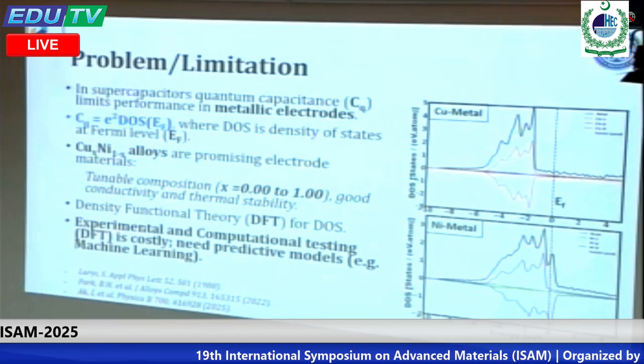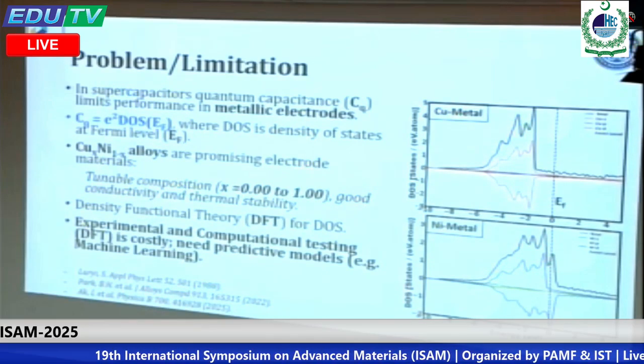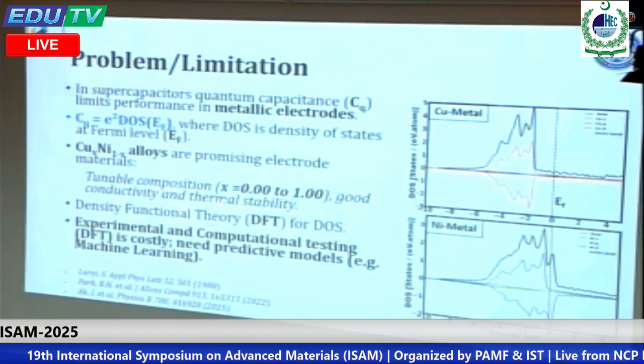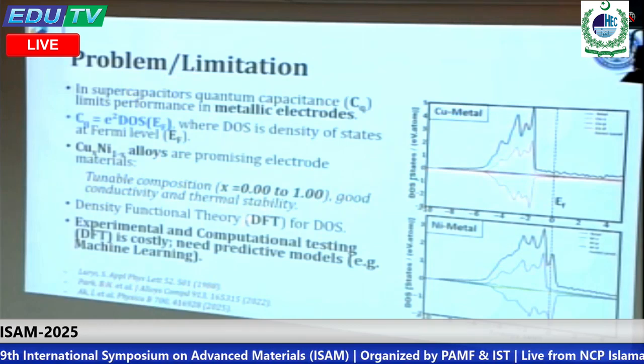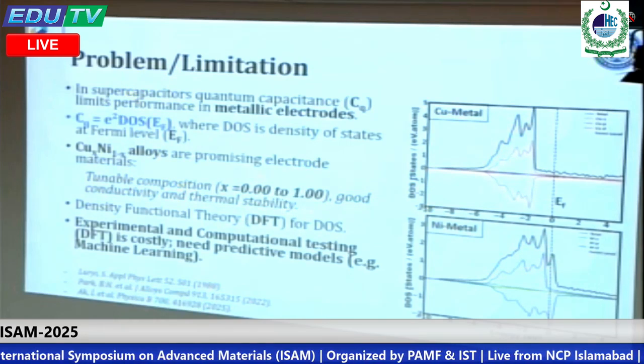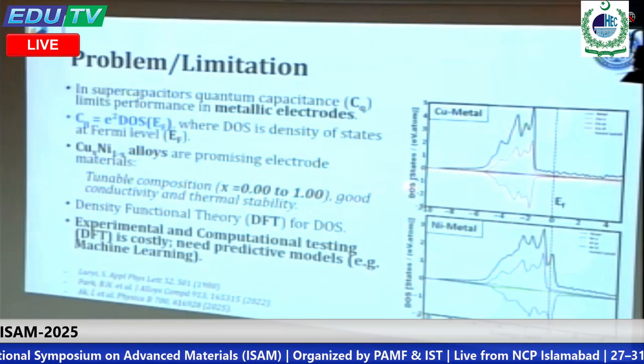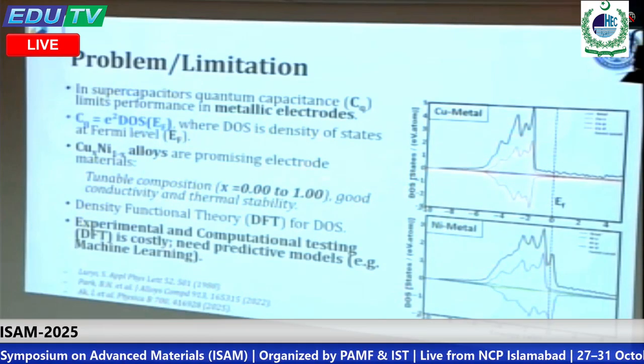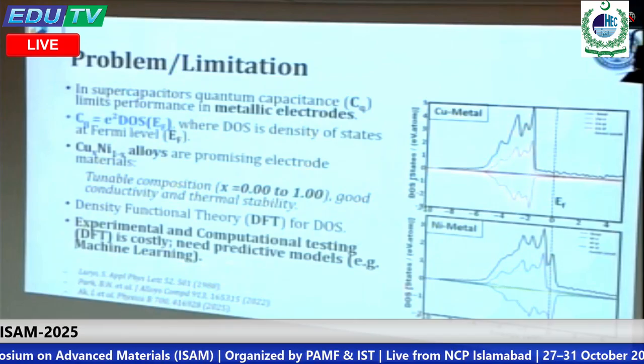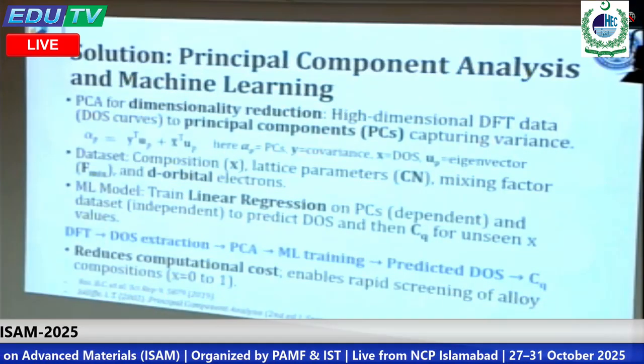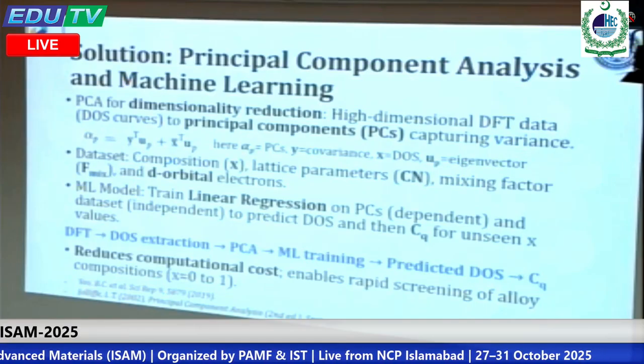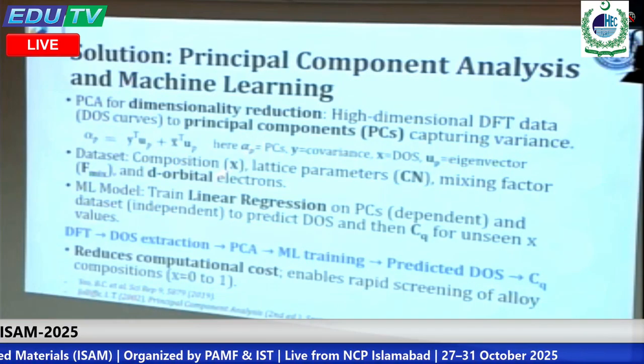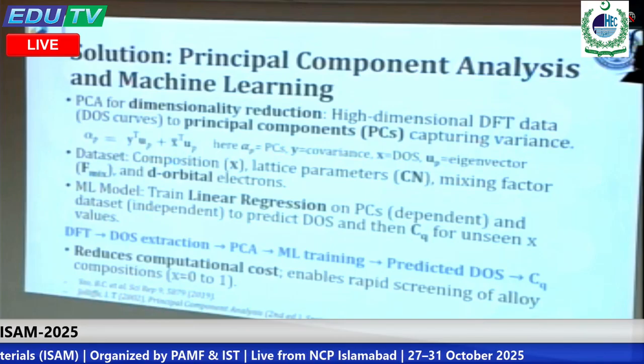The density of states can be obtained from experimental techniques as well as computational methods. Density functional theory is costly, because a DFT calculation requires more than 2 to 3 days for each composition from x equal to 0 to 1. So there is a need for a predictive model, that is, machine learning. In this context, the solution is principal component analysis, an unsupervised machine learning method, along with linear regression.